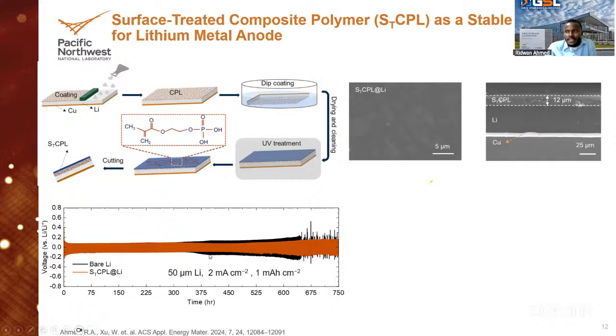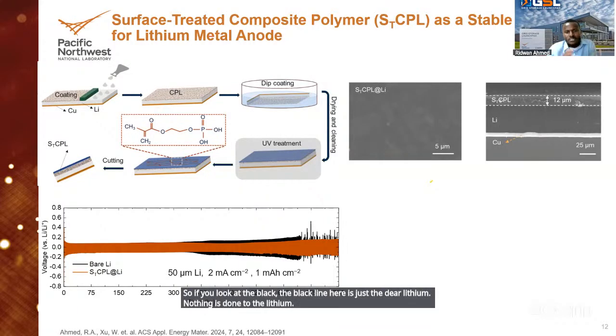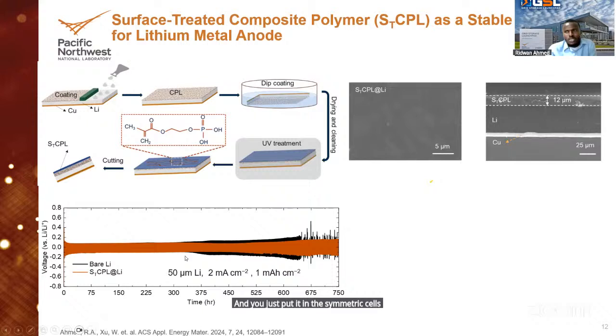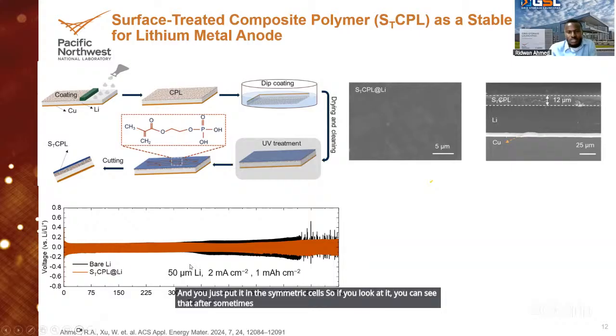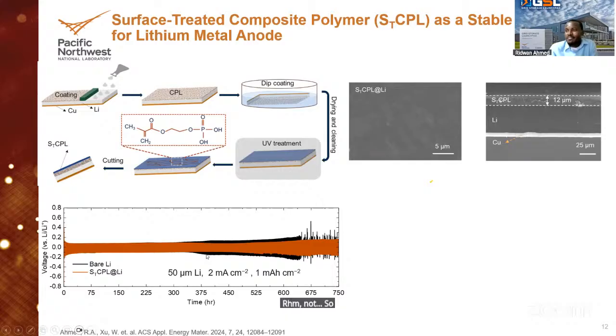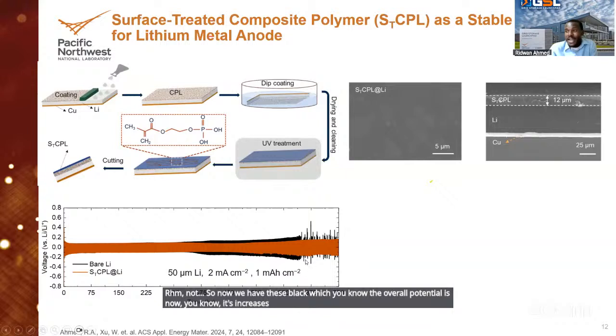So the black line here is just the bare lithium. Nothing is done to the lithium, and you just put it in the symmetric cells. After some time, you can see that the voltage, which is what we call the overpotential, increases significantly relative to the red or orange one. The overpotential increases, and after some time, what happens? It fails. When you have this kind of behavior, we feel like the battery has failed.